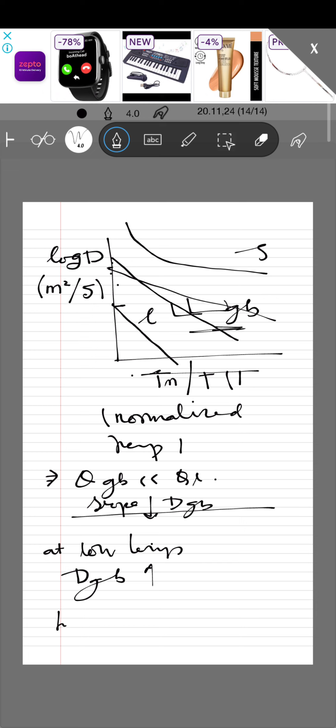However, as the temperature increases, the diffusion of the grain boundary matches with the lattice diffusion. And now, in the case of conventional materials, that means those are not nanomaterials, the volume fraction of the grain boundary is much lower. So the effective diffusion, that is considering all the different diffusional paths, is mainly represented by the diffusion through the lattice.